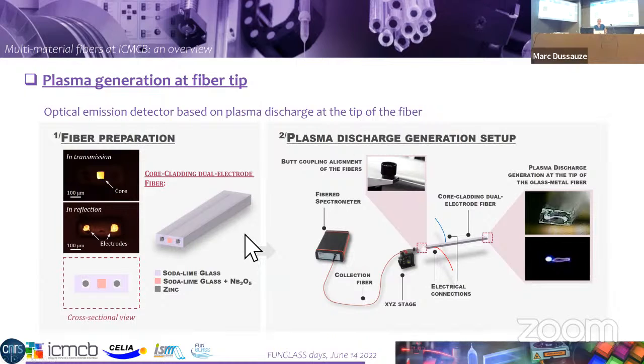And then by connecting a potential to the electrodes and raising the potential, what we observe is that we can generate a discharge at the tip of the system, and then we generate a plasma discharge at the exit. So this plasma can actually be analyzed using the core of the fiber. So we apply the voltage at the exit, and then using the inner fiber, we analyze it.